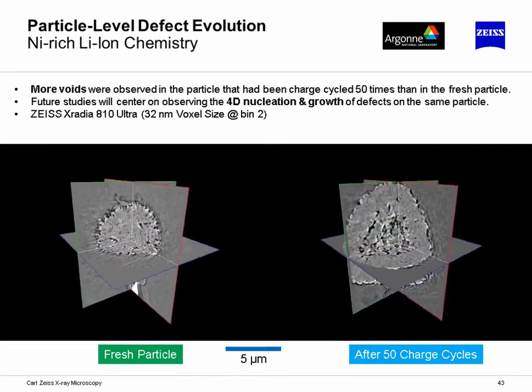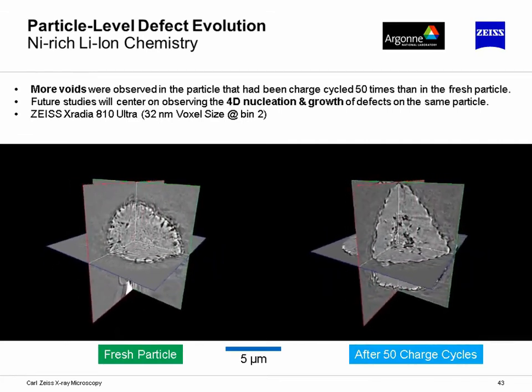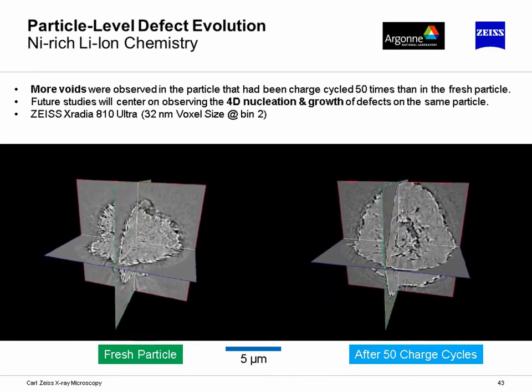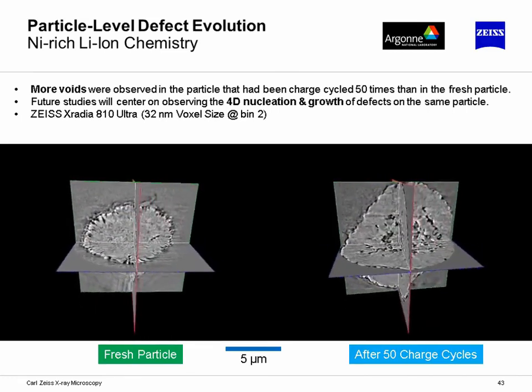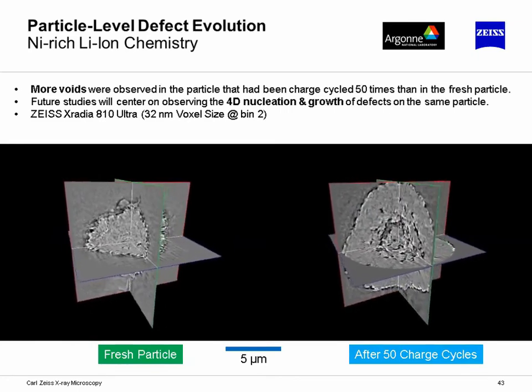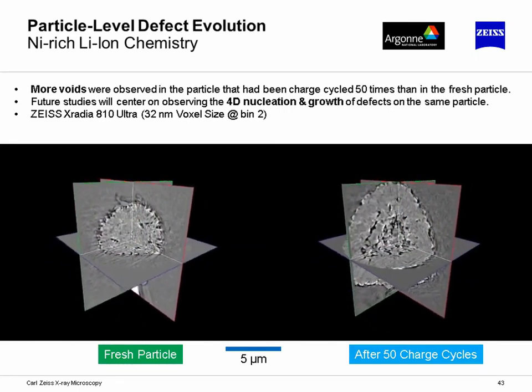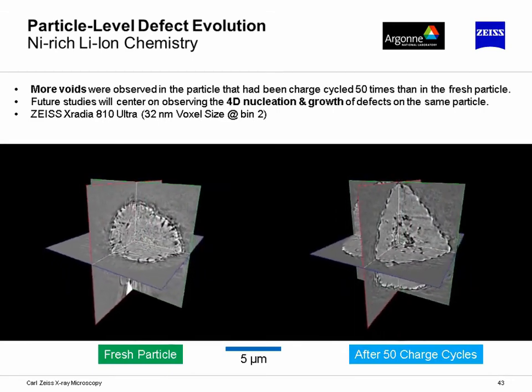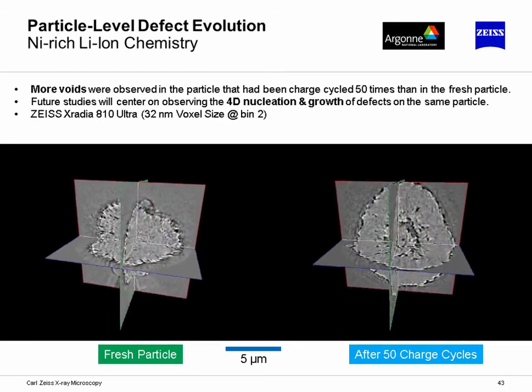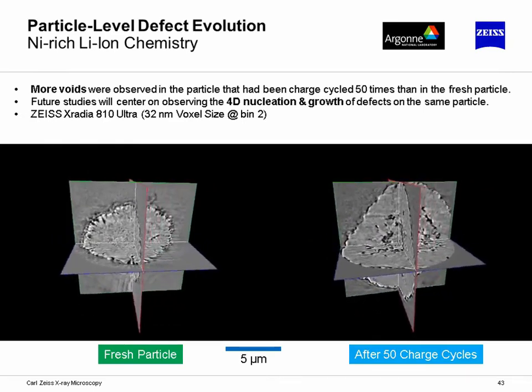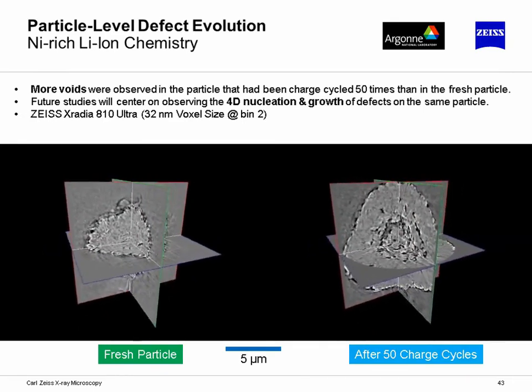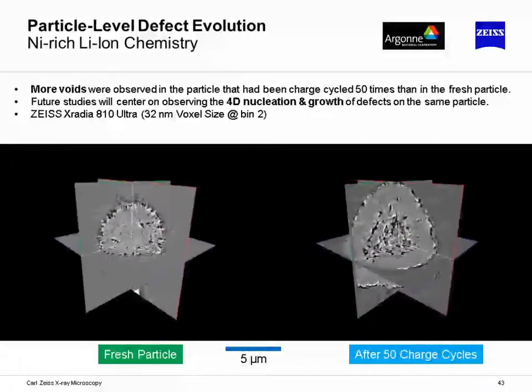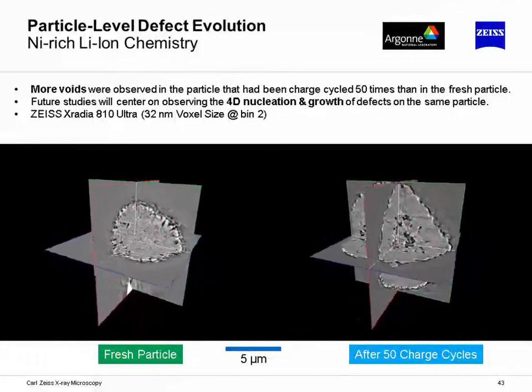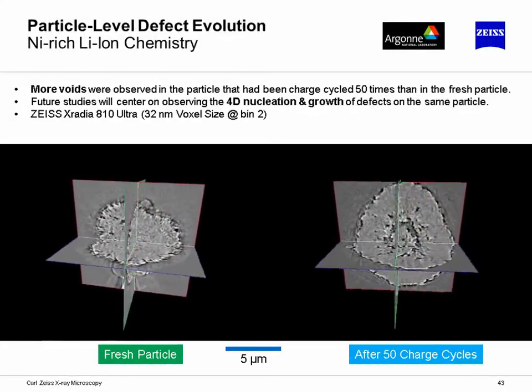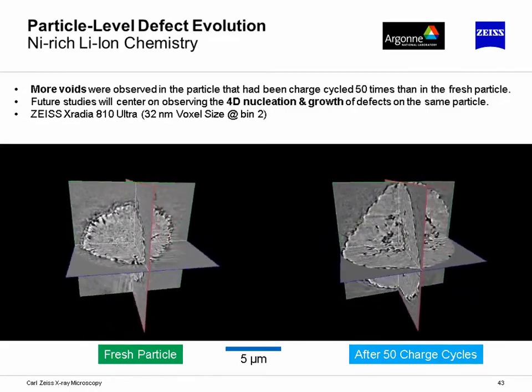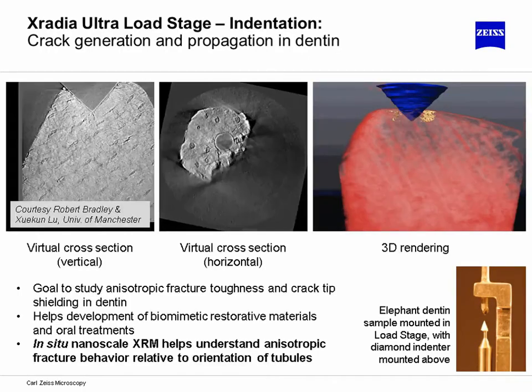Now, I showed a battery result from the Versa just a moment ago. If you really zoom in on an individual cathode particle, this is what you would see. This is maybe 10 microns in diameter here, one that's a fresh particle and the other that is after 50 charge cycles. You see a dramatic difference in the interior porosity, and also some of the cracks can be detected that run to the surface and guide some of the lithiation process in these individual cathode particles of a battery. This is some work done in collaboration with Argonne National Lab, looking at the evolution of individual particles here, and possibly even coupling this to electron microscopy experiments.